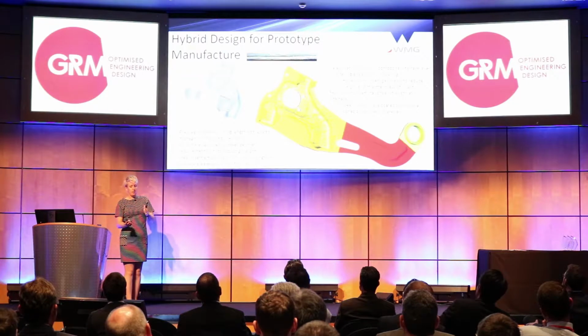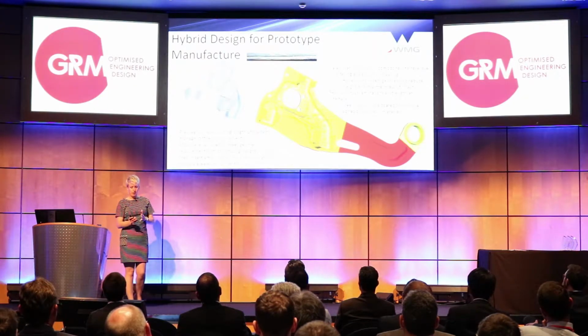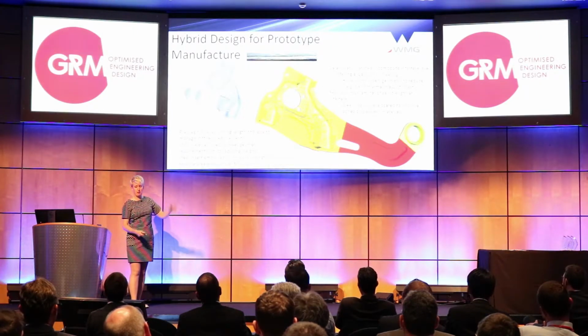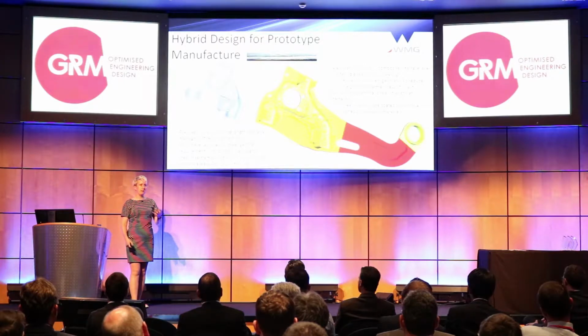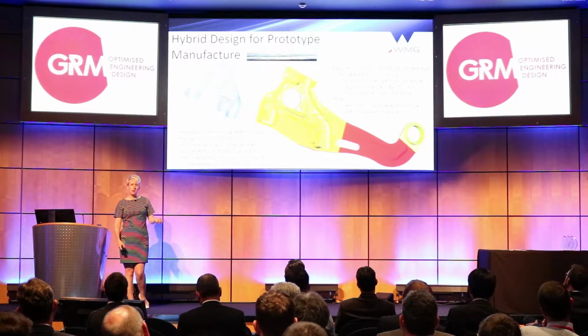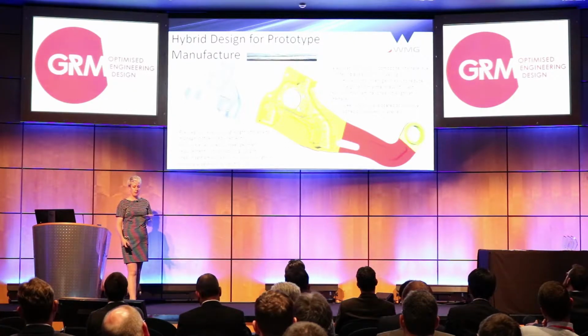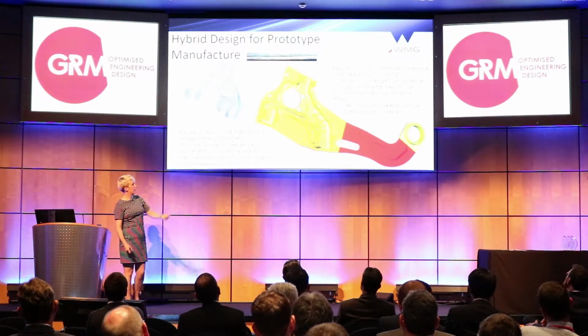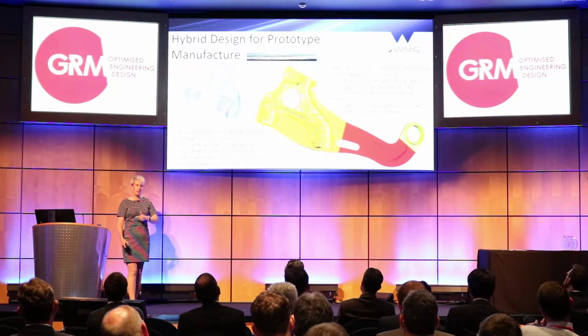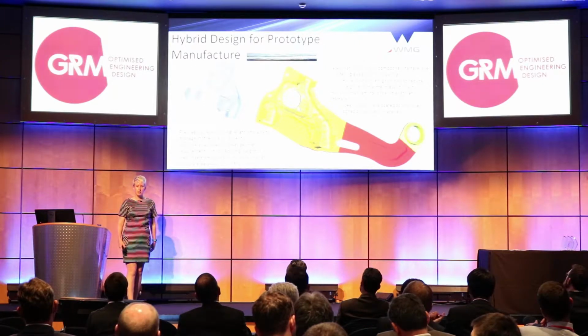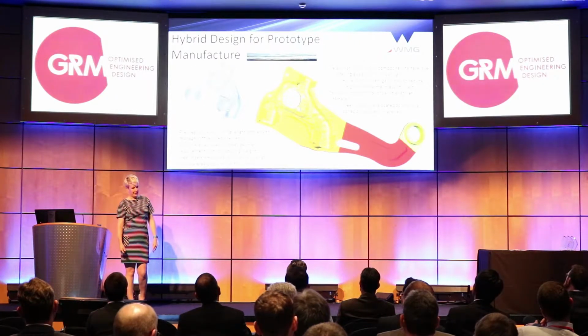This reduced the thermal mass as well as taking mass out of the component, increasing the light weighting. Secondly, the strength of the bond between these layers was under question. When we did our first tests on plaques that you can see there, there was a significant drop in the interlaminar shear strength. So we looked at some coatings that we could put onto the steel to improve this. Using some coatings, the honeycomb structure to decrease the thermal mass, and the honeycomb structure as well to increase the surface area and kind of key in the bond, we overcame that.